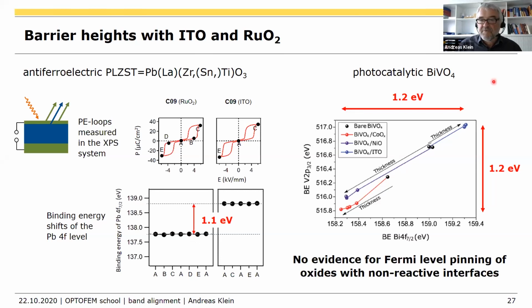We did measurements on bismuth vanadate, which is a very important photocatalytic material. The band gap is something like, I'm not sure, about 2.5 eV or something like this, 2.4. And with our materials, with ITO, ruthenium oxide is not here, but nickel oxide, cobalt oxide, we also get a variation of the Fermi energy of 1.2 eV. And here you see, this is the shift of the vanadium peak, this is the shift of the bismuth peak, and they are the same. So this is a parallel shift of two core levels, which is really good to know that it's really a shift of the Fermi energy.